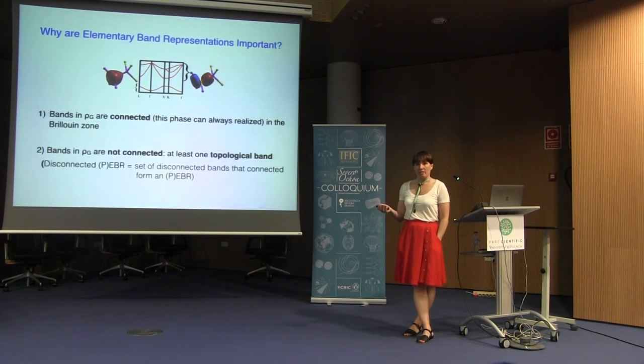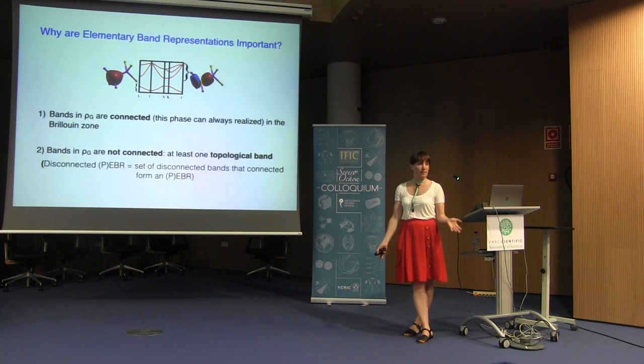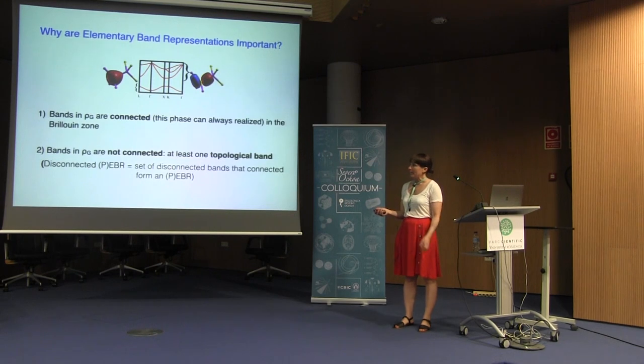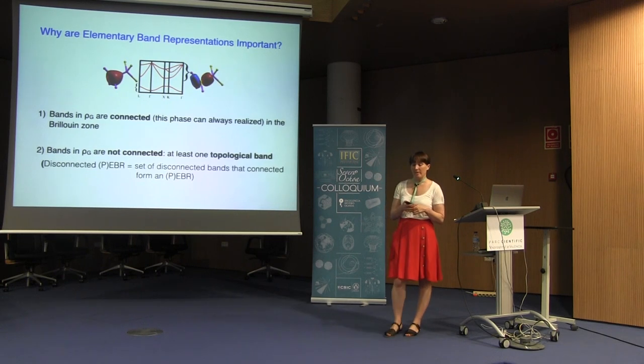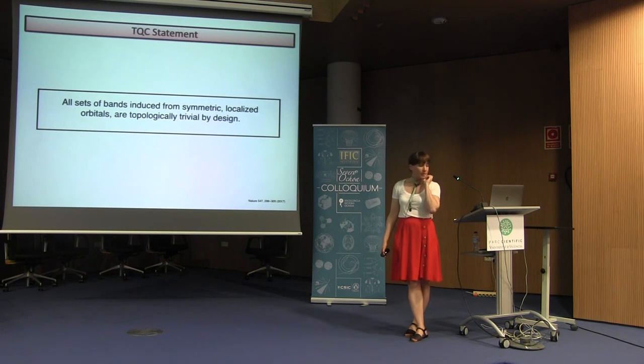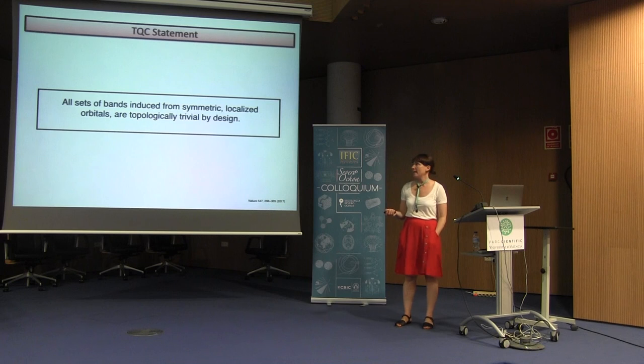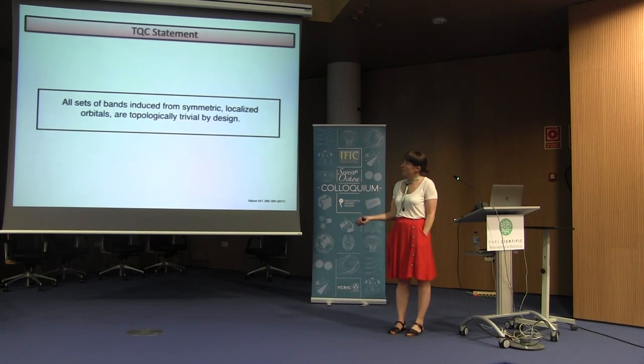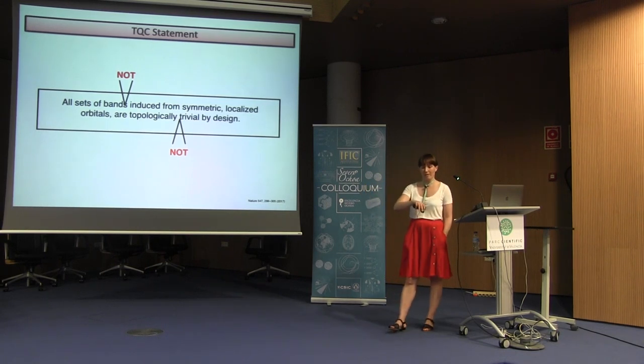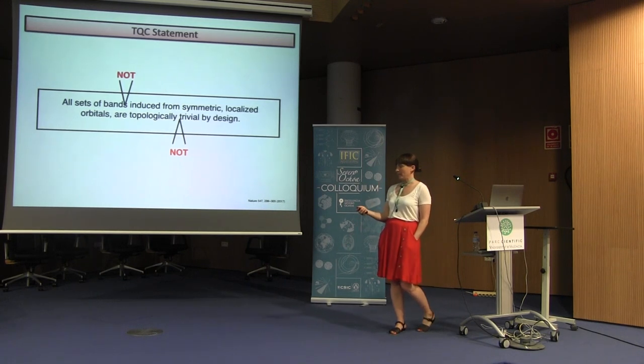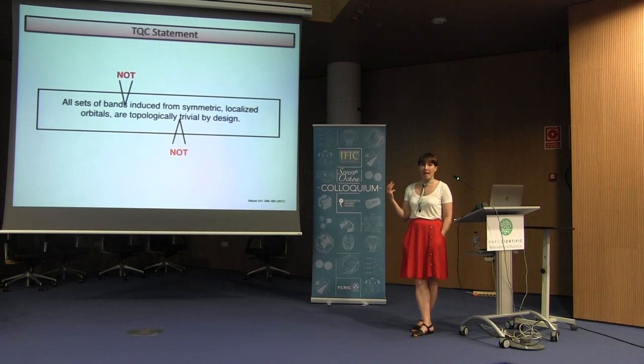So, when we induce a band, an elementary band representation, for example, these bands are induced from these orbitals, we are faced with two simple scenarios. I induce it and I look at reciprocal space and my bands are connected. If the bands are connected, there is no topology. But if I induce my bands in real space and my bands are not connected, then my system displays topological properties. And this has been done without performing any calculation of the Berry curvature or the Berry phase. So the topological quantum chemistry statement says the following: all sets of bands induced from symmetric localized orbitals are topologically trivial by design, and by contraposition, all sets of bands not induced from symmetric localized orbitals are topologically non-trivial by design. So I just need to know, when I have an elementary band representation in reciprocal space, whether the bands are connected or not. And if they are not, there has to be a charge flow somewhere.